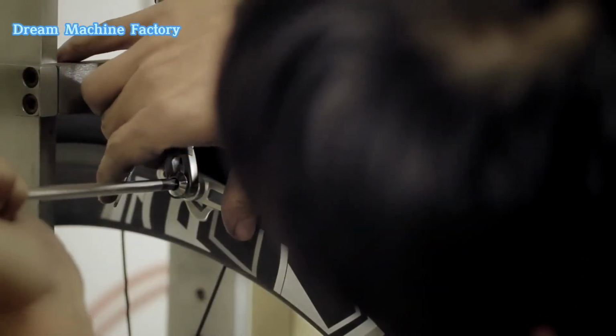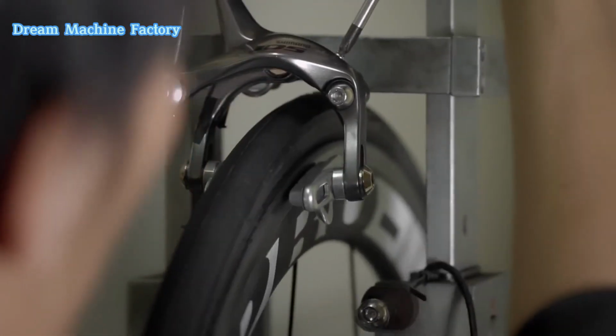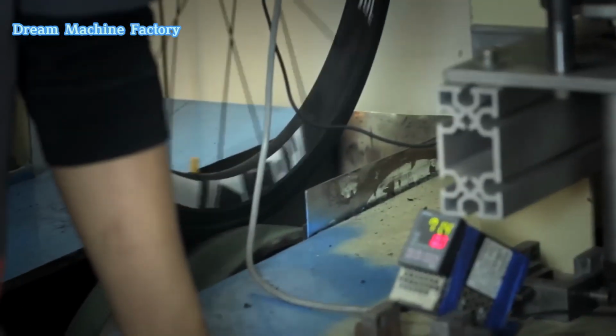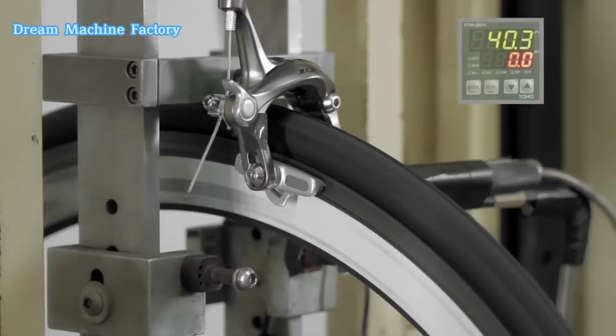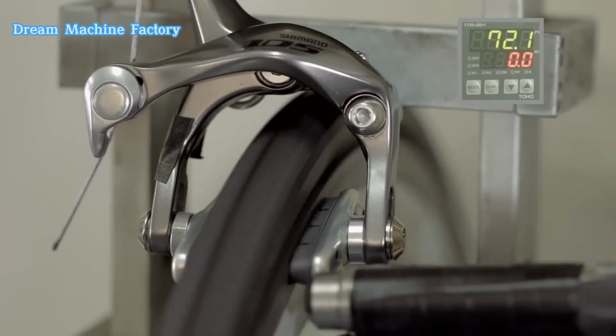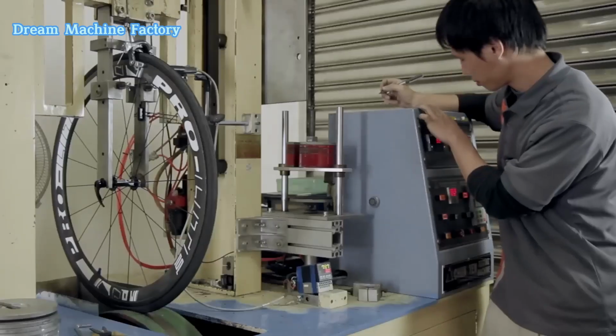A separate long-duration test evaluates the wheel's response to sustained braking pressure and high temperatures. By increasing the speed and applying constant weight, this test identifies potential failures and ensures the brake surface can handle prolonged use without compromising performance.